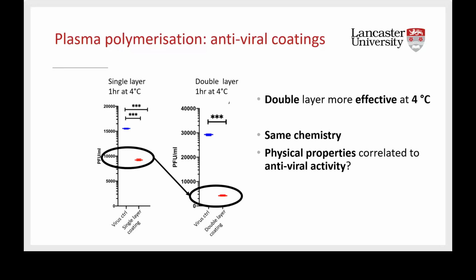We're trying to understand why, because if we find out why, maybe we can improve the properties of these coatings to be even more antiviral. First, we checked the chemistry, but we noticed that the chemistry is exactly the same, so it cannot be responsible for these new properties. So then we tried to look at the physical properties. Maybe one of them is correlated to antiviral activity.